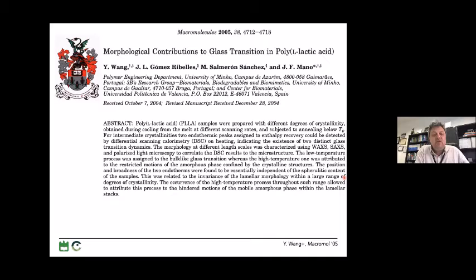So in this publication, just to give you an example that was published with the group in Valencia, we analyzed the effect of the extent of the crystalline structure on the glass transition of polylactic acid, which is a very well-known polymer used in several biomedical applications. So we discovered that the amorphous content between the crystalline lamellae in the spherulites presented a very different dynamic behavior as compared with the free or unconfined bulk amorphous phase.